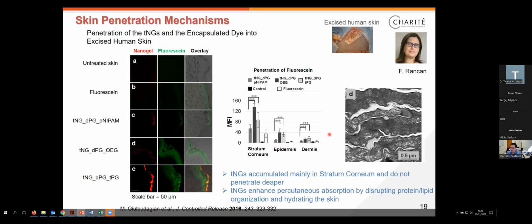We also analyzed what happened with the skin when we incubated the skin with our nanogel solutions. And we could see that the skin very, very quickly hydrates. And as I mentioned before, this expelling of the water when we cross the transition temperature with the nanogels is something that is interesting to have in these sort of systems, because, as I said before, water is known to be a natural penetration enhancer of the skin.